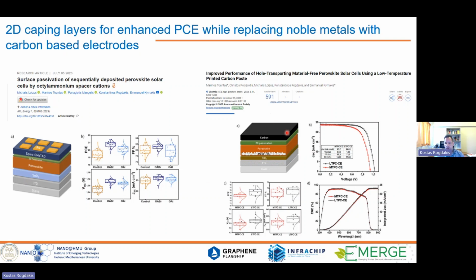And in this study on the right, we replaced the noble metal contacts that are usually gold or silver with carbon-based material, and we demonstrated even better performance compared to noble metals. So replacing noble metal electrodes is a very important direction because we can have a fully recyclable device, and of course, the manufacturing cost goes down.